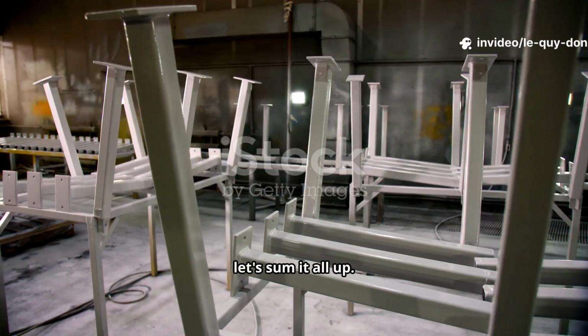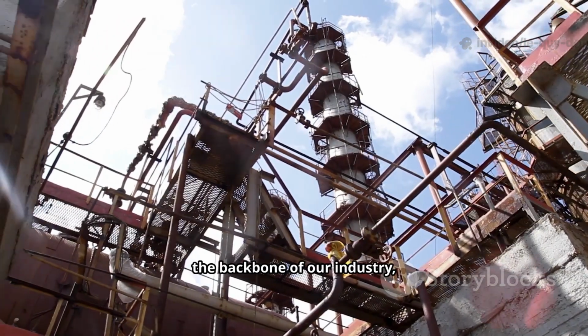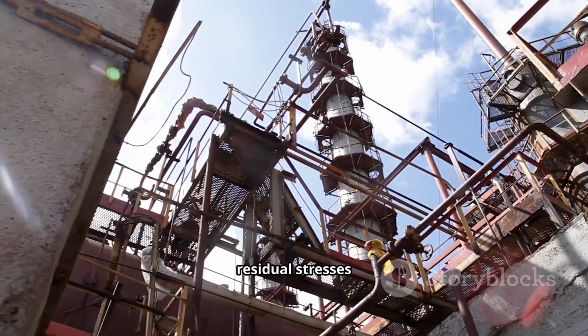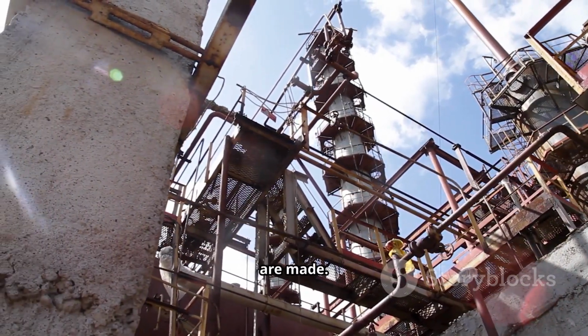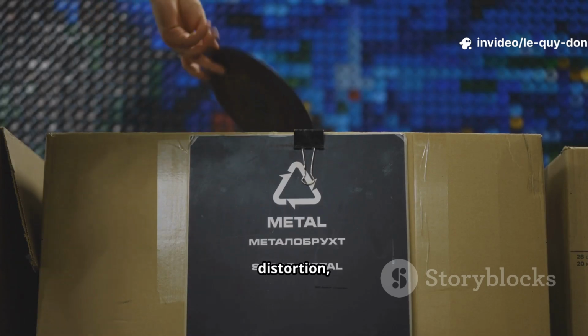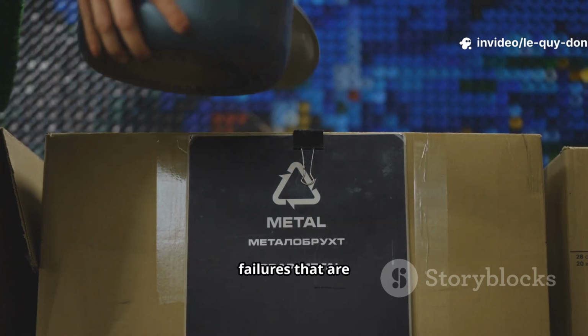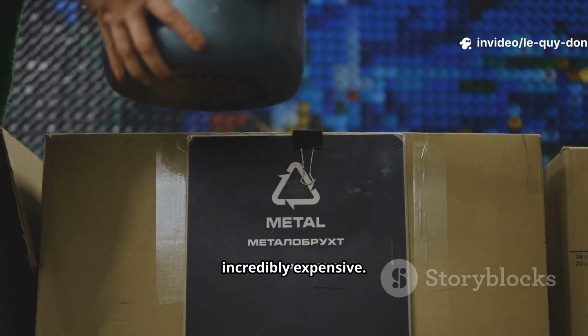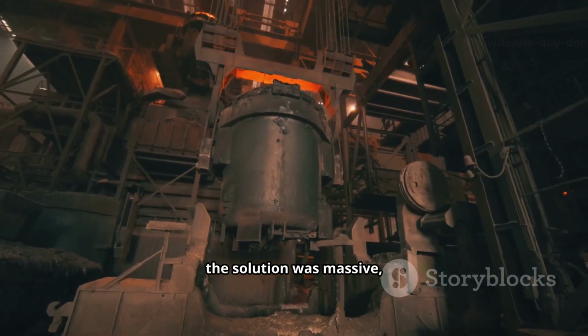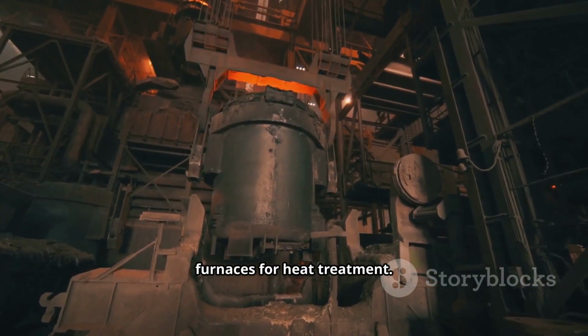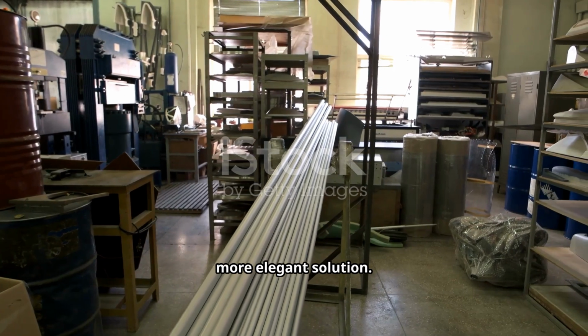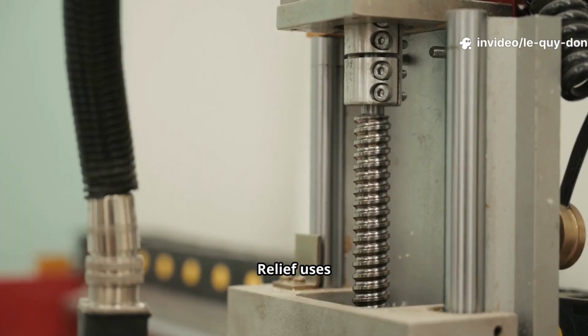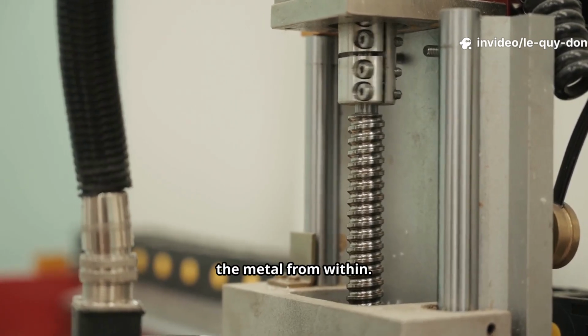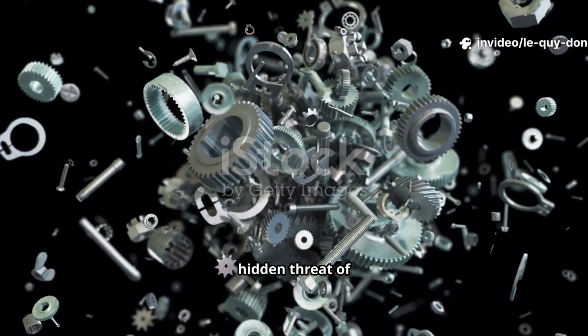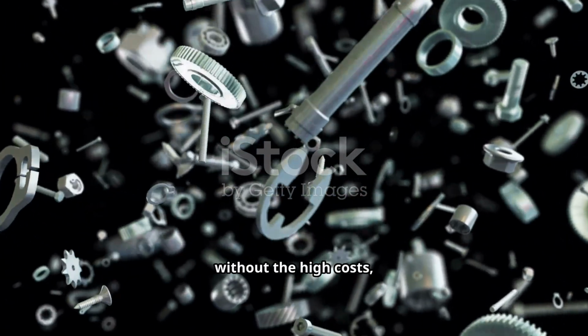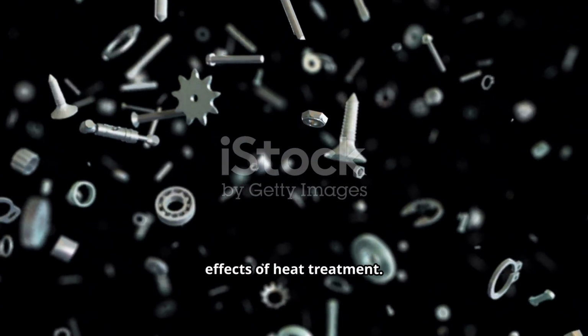So let's sum it all up. We know that large metal structures, the backbone of our industry, contain hidden residual stresses from the moment they are made. These stresses lead to cracks, distortion, and catastrophic failures that are dangerous and honestly incredibly expensive. For years, the solution was massive, energy-guzzling furnaces for heat treatment. But today, we have a smarter, more elegant solution. Vibratory stress relief uses controlled vibrations to relax the metal from within, neutralizing the hidden threat of residual stress without the high costs, environmental impact, or negative side effects of heat treatment.